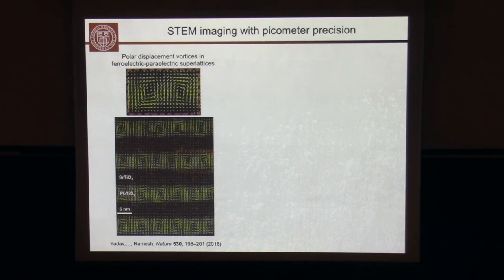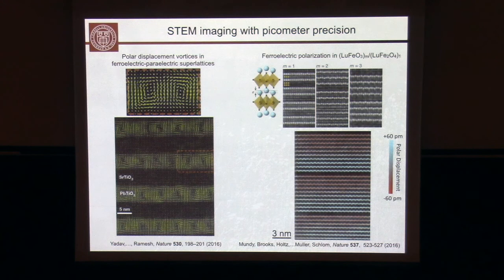And an example from Cornell, we can also look at a different system. I don't want to go too much into the details, but here we are also looking at the ferroelectric polarization of the material. What's interesting to note, not only can we extract the polar displacement, you see this is from 60 to negative 60 picometers, but we can also convert that directly into polarization, and that means you have a local measure of the polarization in the superlattice. You see that we have a polarization vector pointing downwards at the upper part of the superlattice and upwards in the lower part. Okay? So we can measure order parameters with high resolution.